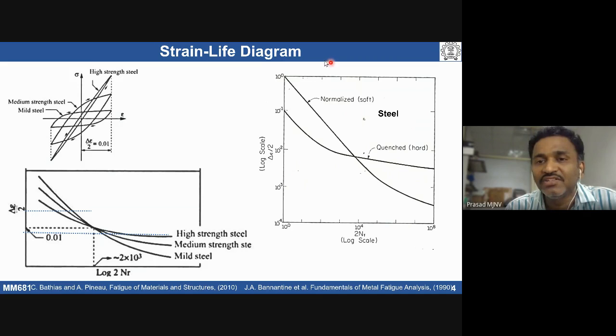Am I right? Yes, sir. The low cycle fatigue regime is very clear, because a crack is going to initiate in all of them, since we are already giving enough stress or strain amplitude. That can take care of crack initiation. But the crack initiation is more in the quenched steels, the density of cracks is more in the case of quenched steel as compared to normalized steel.